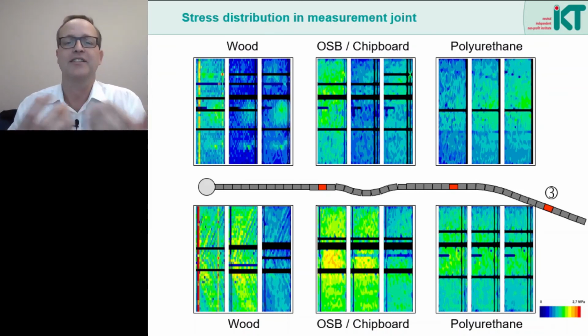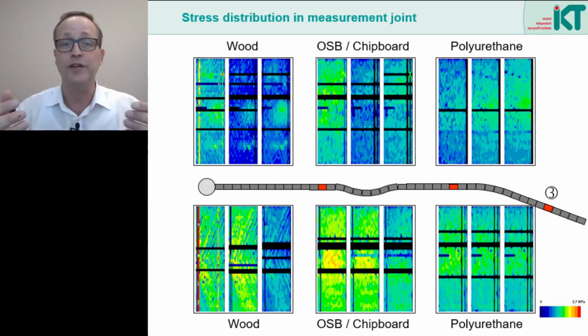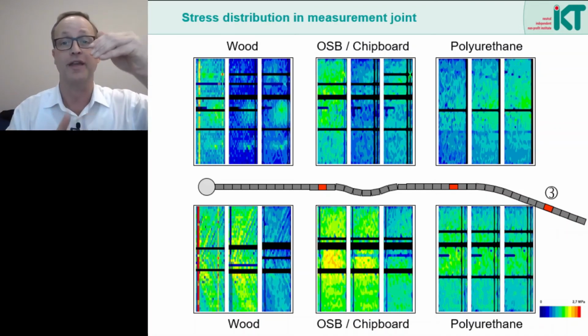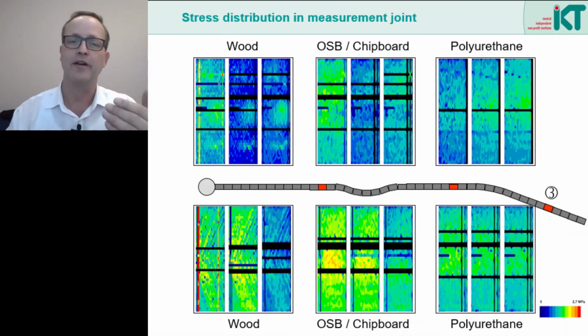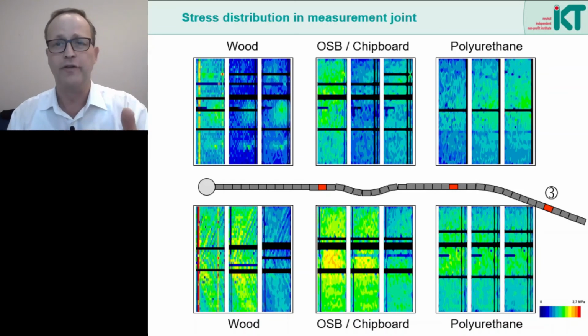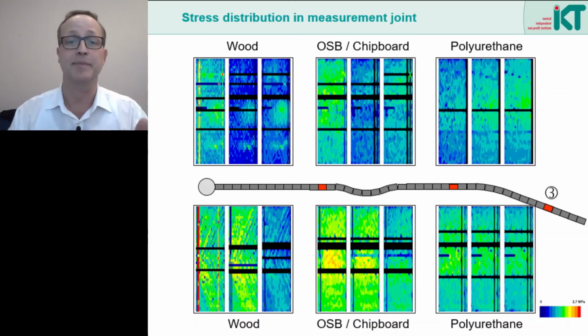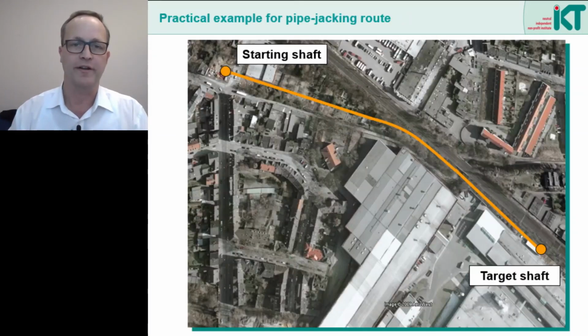Well, the answer is simple. The loads are now increasingly transmitted via the crown and the invert of the pipe. However, this means that after a curve, now higher risks can be expected for the crown and for the invert. If they are subjected to higher stresses because of a rise in jacking forces, then this too can lead to cracks or spalling. So we have learned, the pipe string geometry is not ideal.